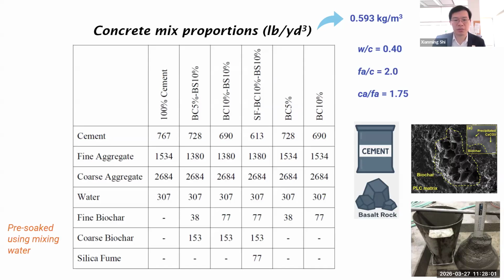And we pre-soak these biochar, as I showed earlier, before grinding is coarse biochar and after grinding is fine biochar, less than 150 microns, which happens to be about twice the size of human hair. So we use these symbols, fine biochar is BC, coarse biochar BS. Also, in one of the mix designs, we also explore adding 10% of silica fume, yet another industrial byproduct to replace cement. So we got 1, 2, 3, 4, 5, 6 mix designs.